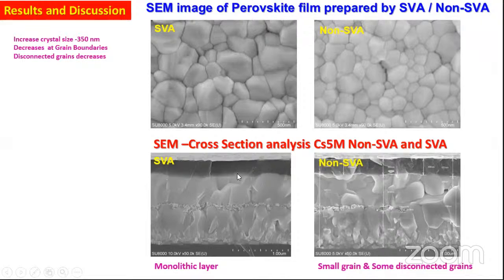When we check the cross section, the perovskite forms a monolithic layer, and there is very good connection with the TiO2. This one is the TiO2 layer for the ETL. This one is the hole transport layer. This one is the counter electrode. We can see this is completely merged with both the TiO2 as well as the Spiro. Whereas in the case of the non-SVA method, we can see the grains are very small, and we can see some disconnected grains.